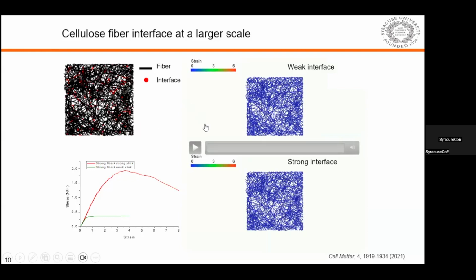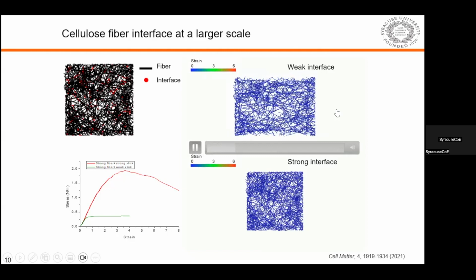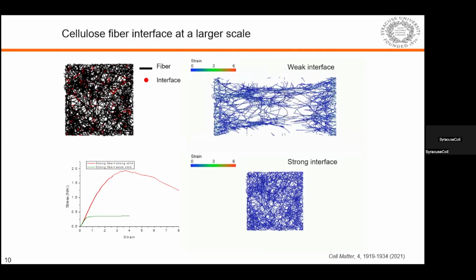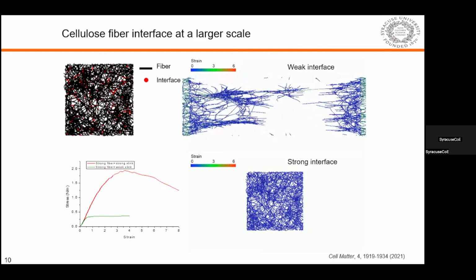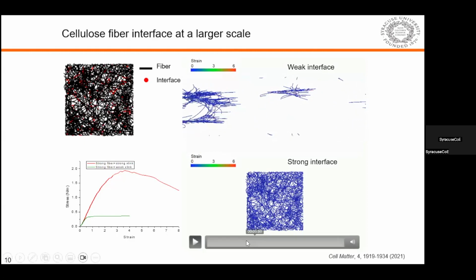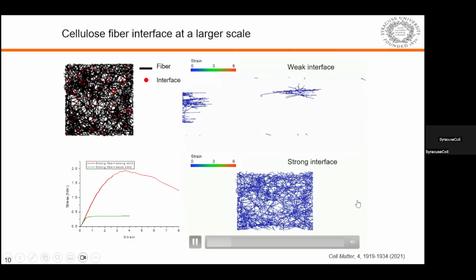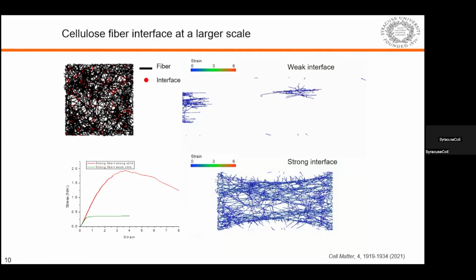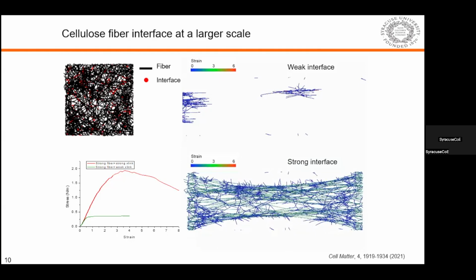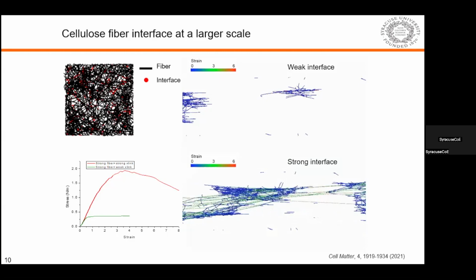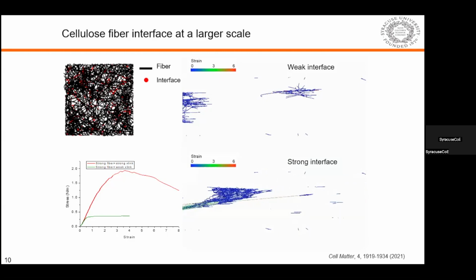But then we can use our simulation to hypothetically tell how significantly the mycelium can contribute to the strength of the composite. For example, this is a network of wood fibers with weak interaction. If you don't have mycelium, the wood fibers cannot strongly attach to each other. They don't have strong entanglement. That's why once you pull them, they break easily. But if you have a strong interface between those wood fibers, starting with exactly the same geometry, then during the loading test you see those interactions strongly contribute to the strength and energy dissipation. And you have a lot of wood fibers you need to break before it ruptures.